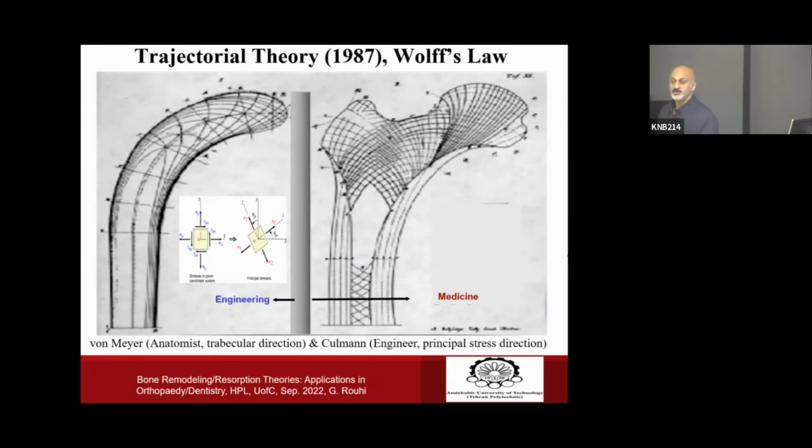In bone remodeling, the vertical axis is the rate of change of apparent density or the rate of change of modulus of elasticity. We would like to have our bone in this specific range. This is a mechanical stimulus, but we don't know what it should be. Strain, stress, strain energy density, nobody knows, honestly speaking. Let's assume a strain, okay?